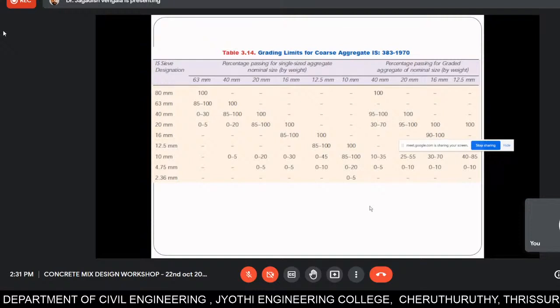If you find 20 mm down is a single sized aggregate, you mix 10 mm down aggregates to make it graded, and make sure you use a graded aggregate in your concrete mix. So these are the limits given by IS 383. One has to make sure whether you have a graded aggregate or not before using it in concrete.